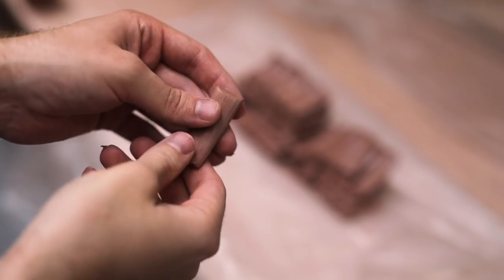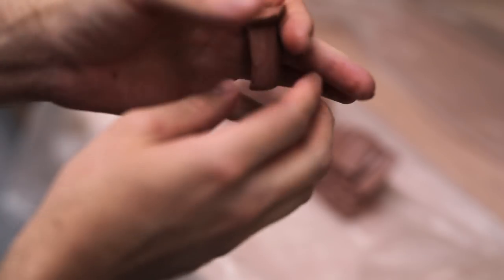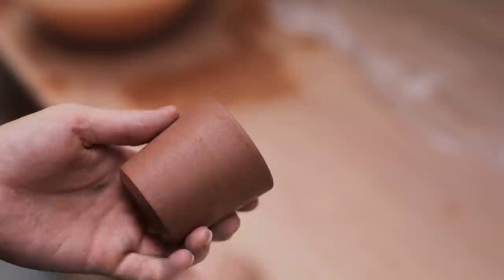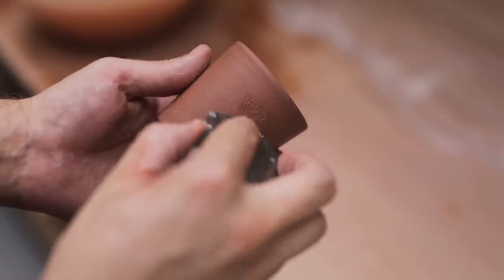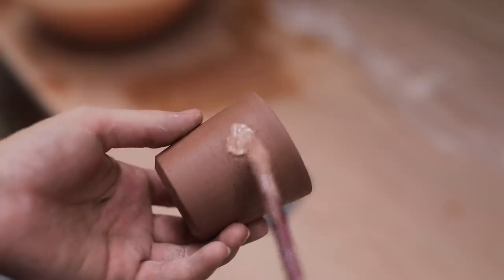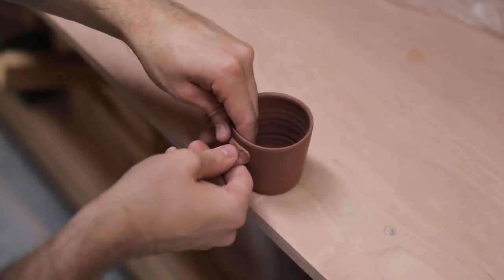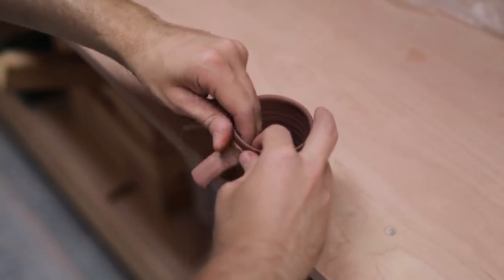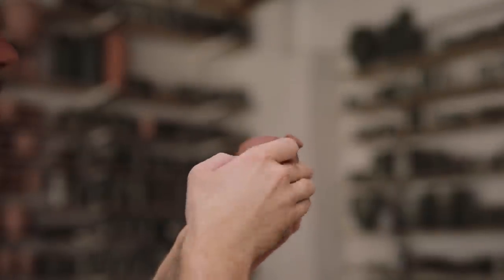To begin the handling process itself, I take one of the blanks and tap out a flared end. This flare will provide me with material which I can easily blend into the body of the espresso cup. I then score the area where I want the handle to go, and then on top of this I dab just a little bit of slip, and before I place the espresso cup back down on the table I make sure to quickly wipe it clean so that no burrs of clay stick into the freshly finished base. I then push the handle firmly onto the espresso cup and blend in that flare of clay all the way around the join, making it as seamless as possible.